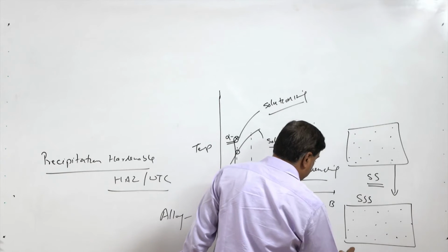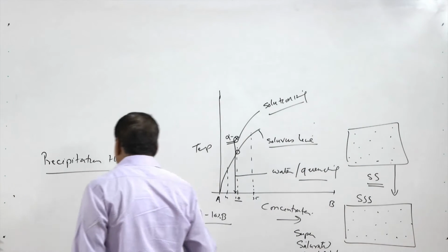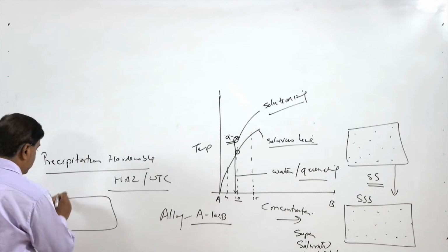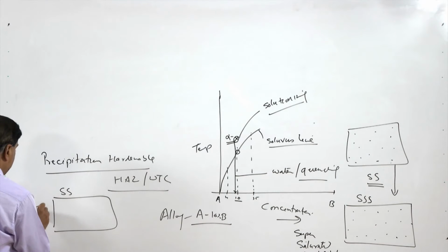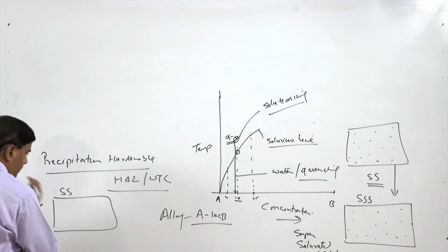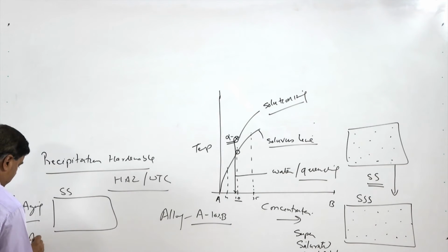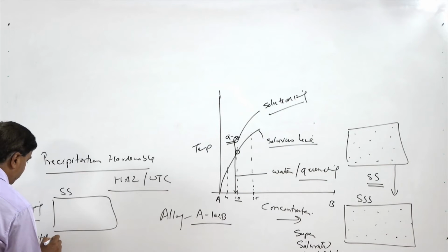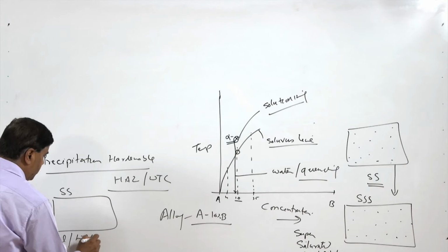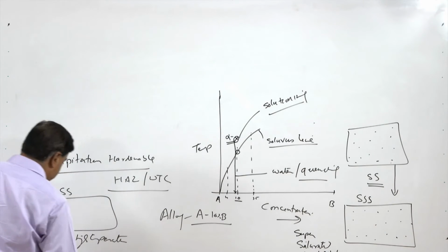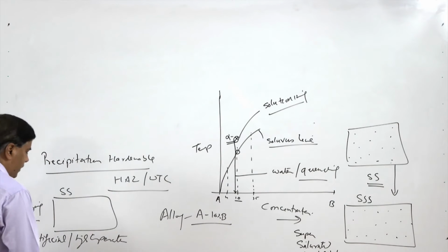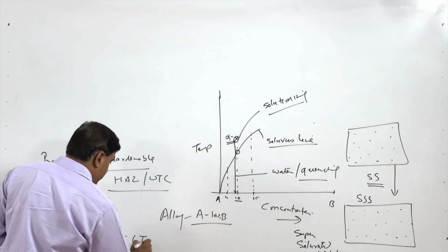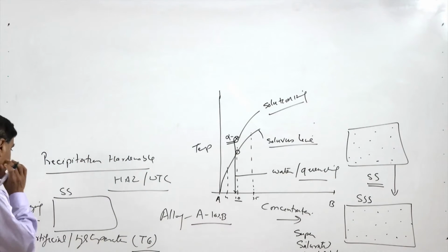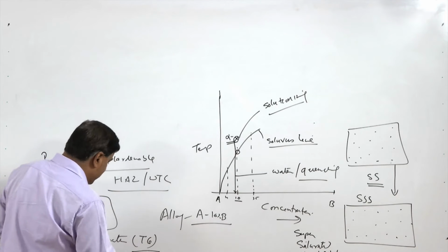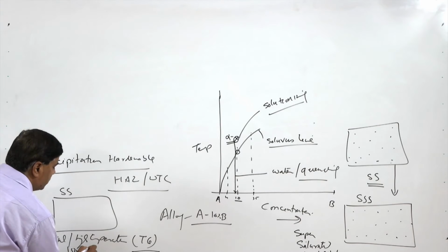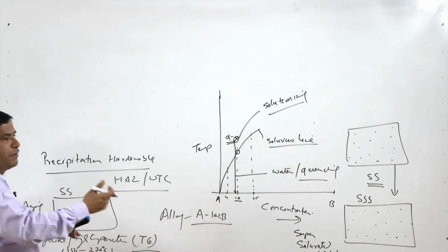This supersaturated solid solution is then subjected to aging. The aging can be at two levels. The supersaturated solid solution subjected to aging means it is allowed to hold for some time. So, if this aging is done at high temperature, meaning artificial heating is done to have a high temperature exposure, it is termed artificial aging, and this is typically termed T6 treatment or temper condition. During this exposure at a high temperature, which is normally, say for aluminum alloy, 150 to 230 degrees centigrade, it may be different for different metal systems.